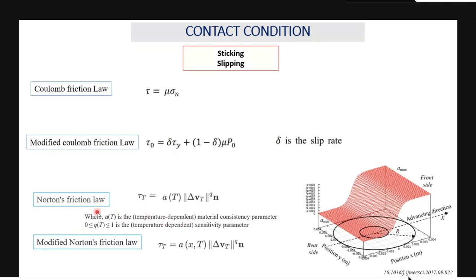So Norton friction law is better in many cases because it includes the influence of the material property on the contact condition. Even though there is some problem, because when you are considering these cases, it is not showing different friction conditions from the tool center to the periphery. Actually, from the tool center to periphery, you will have a different contact condition. These models will not have any functions to represent that.